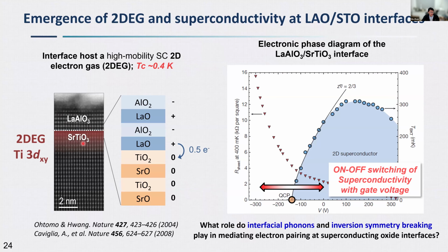And this sample is grown at high temperatures, and the LAO layer is crystalline. Both materials are insulating, but when you grow them to form this interface, they form a 2D electron gas due to the electron transfer from the lanthanum oxide layer to the STO region. And upon tuning the charge doping, you can tune this from an insulating oxide to a superconductor, although the TC is extremely low, about 200 to 400 millikelvin.